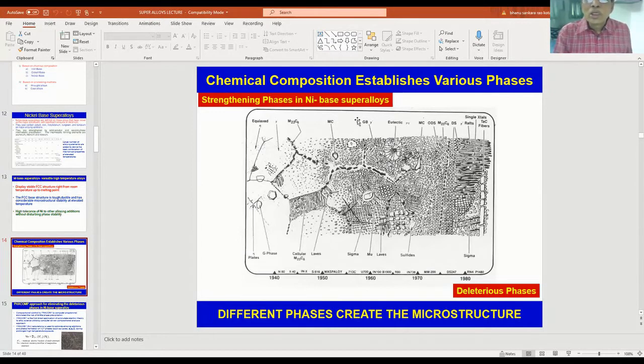I told you titanium and molybdenum will be there. They form some type of MC carbides. M is the metallic element that gets substituted, can be titanium carbide and other things. Subsequently, if titanium and molybdenum are tied up in this type of carbides, what will happen? Sufficient amount of titanium will not be available for you to precipitate your gamma prime, which gives strength to the matrix. Molybdenum is required for providing solid solution strengthening at elevated temperatures. If the molybdenum is tied up in this type of carbides, then sufficient molybdenum will not be available to provide high temperature strength to the matrix in the form of solid solution strengthening. So all these are undesirable.